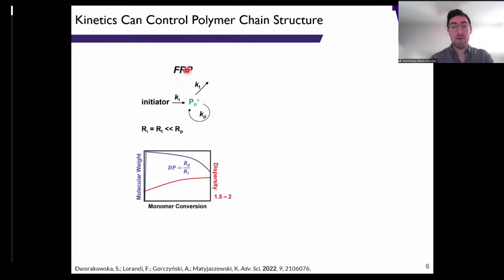The industry favorite, FRP, or free radical polymerization, involves, typically with a thermally labile initiator, the generation of some small amount of free radical initiating species, and this is governed by a particular rate constant, Ki. This starts to interact with your unsaturated monomers, and then you engage in propagation steps. In this case, propagation is really, really fast relative to initiation and chain termination events. So you end up with really, really high molecular weights at short monomer conversions. And then this starts to taper out as a function of time. We'll talk a little bit more about what molecular weight on the left-hand side and this dispersity in red on the right-hand side mean in just a bit.